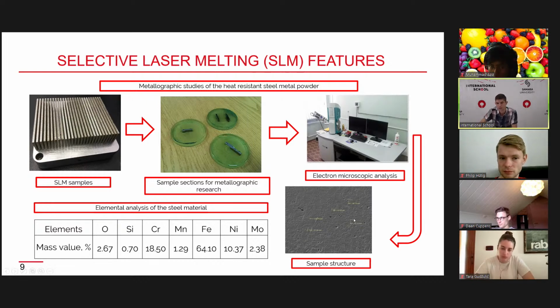You see on the right side of the screen, there's some tiny structure. We can see, is it good enough? Which mode is better? And again, elemental analysis of steel. So this is the percent mass value of the compounds of this sample. It has oxygen, chromium, molybdenum, ferrum. It mostly consists of the ferrum element, and again some nickel and molybdenum compound.